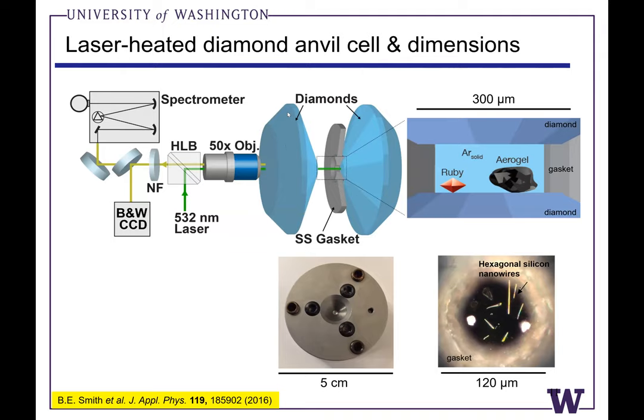And this is really what my group has been using predominantly at the University of Washington. I first started learning about this as a postdoc at the Lawrence Livermore National Lab. And the idea, in case you've not worked with a laser-heated DAC before, is effectively just to have a focused high-power near-infrared laser focusing into the center of the chamber. We have two diamond anvils counter-opposed, and we can load the diamond anvil cell with neon, with argon. Argon is sort of our standard workhorse quasi-hydrostatic pressure medium. We add a ruby crystal. We use ruby luminescence as our primary pressure sensor.